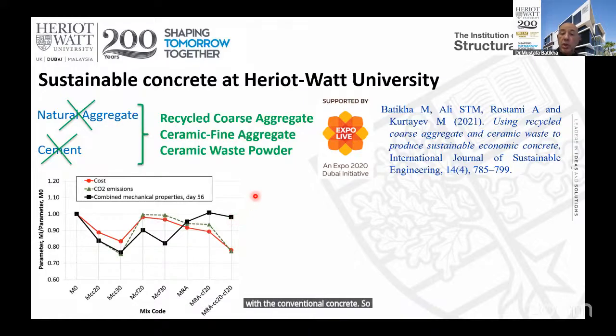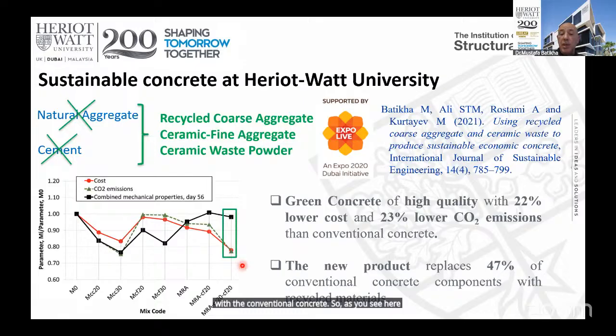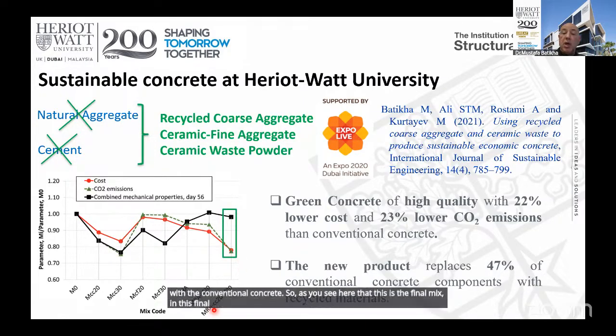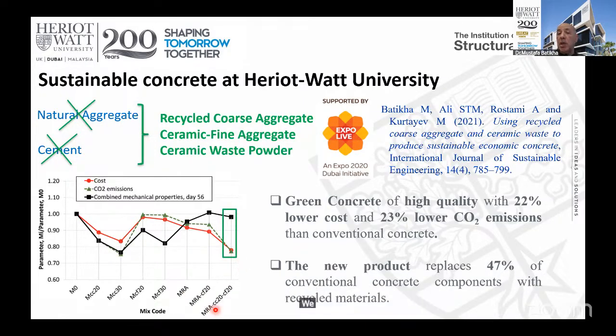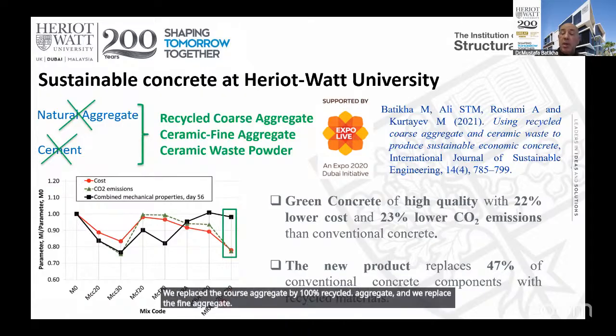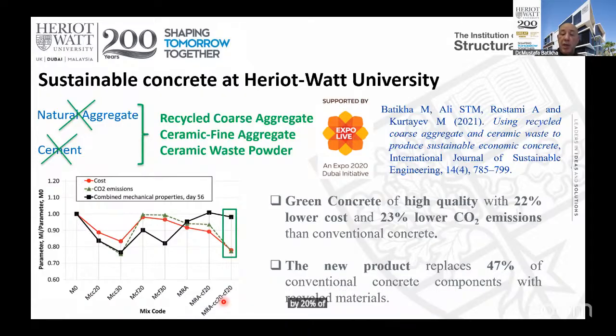So as you see, in this final mix, we replace the coarse aggregate by 100% recycled aggregate, and we replace the fine aggregate by 20% ceramic fine, and we replace the cement by 20% ceramic waste powder. The result was very promising. So you can see that we obtain high quality, by the way.